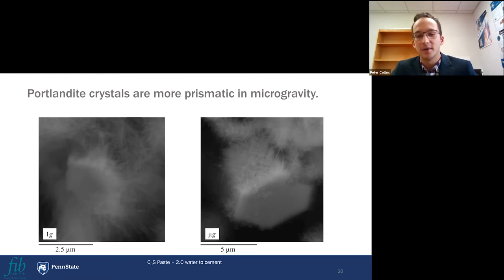This is from that same tricalcium silicate paste at a water to cement ratio of 2.0. On the left is a terrestrial gravity crystal, and that is a portlandite crystal, or the CH. You can see the nice hexagonal face there, but you can see there's no real depth to it. It starts to tail off, and you can see the void behind it. All of the needles that are on there are the calcium silicate hydrate. But on the right, you can see that nice hexagonal face again, but you can see there's some depth to it with the CSH growing off of it.